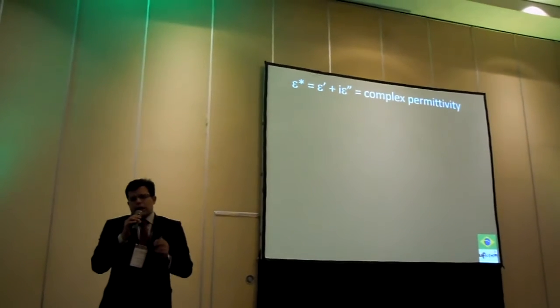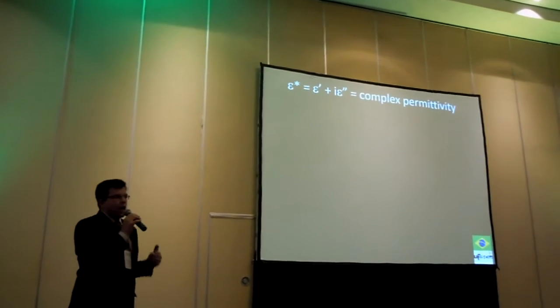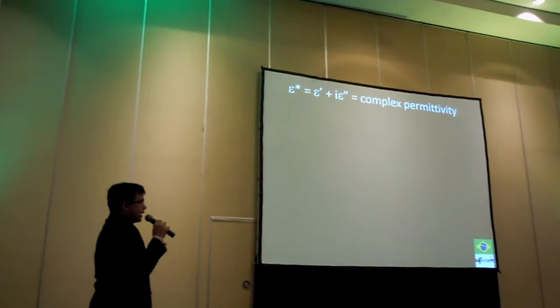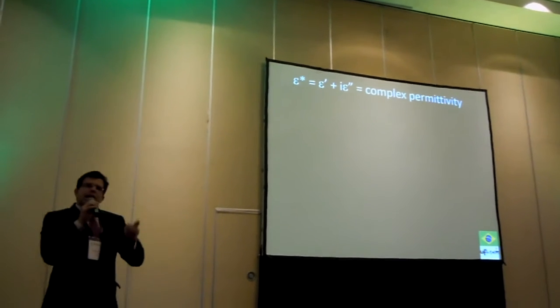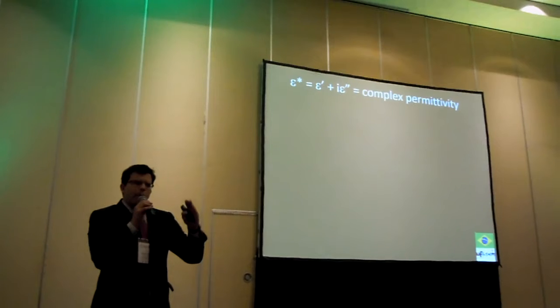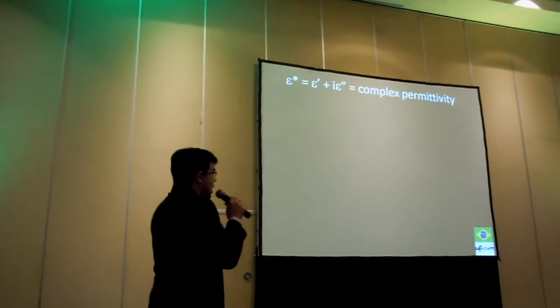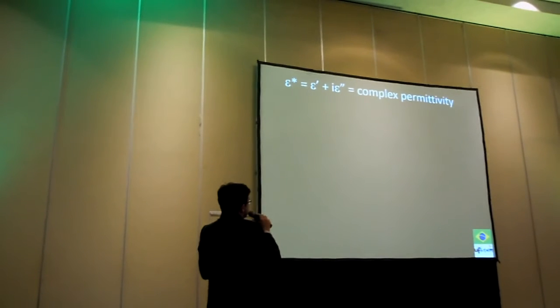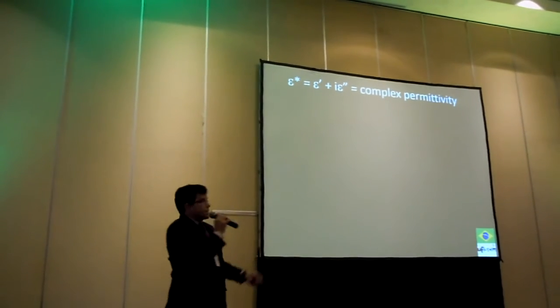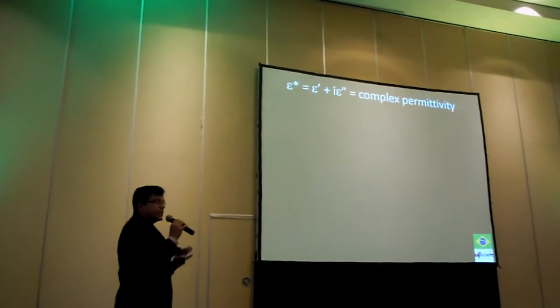Important to remember, the application of this kind of nanocomposite that we are making happens in AC current. So we are looking for dielectric permittivity, but in AC current, dielectric permittivity becomes complex permittivity and has two components: the real permittivity and the imaginary permittivity.